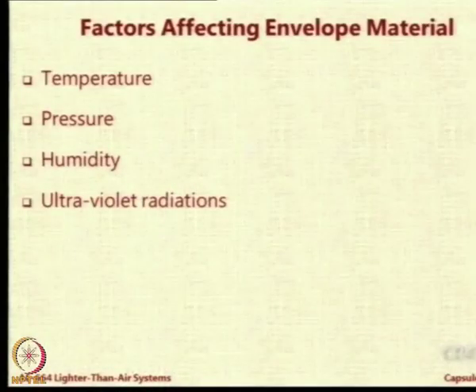Humidity is a very big factor. We sometimes ignore it, but although the numerical value of the effect of humidity on lift generation is only 2-3 percent, the effect of humidity exposure on the strength of the fabric is extremely large and one has to quantify this number by doing experiments. UV radiations are another killer which can grossly lower the strength of the fabric after sustained exposure.